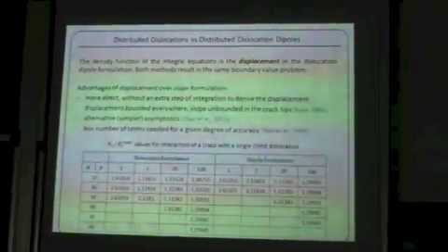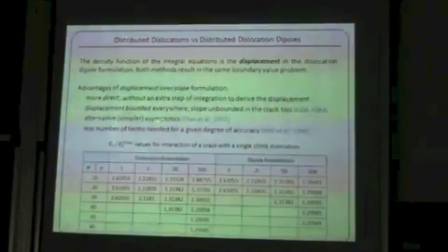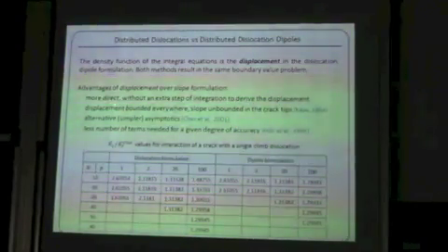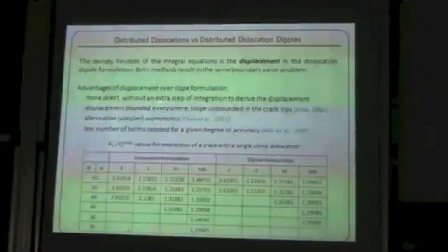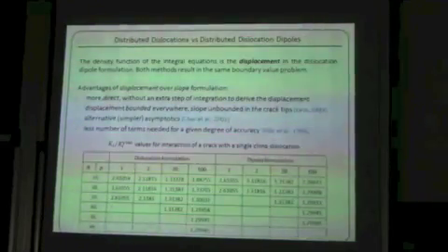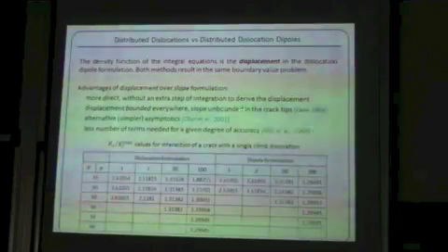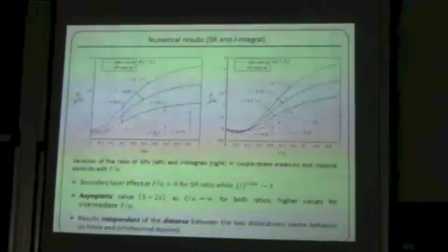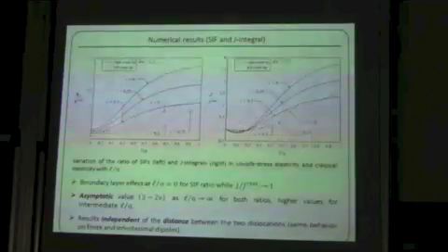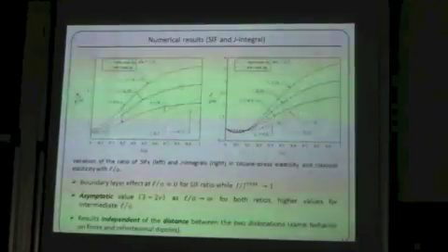Using both approaches. So we have written some advantages of this methodology that are reported by other authors as well. The most obvious is that this methodology is more direct, because we do not need an extra step of integration to obtain the crack face displacement, and also that the displacement is bounded everywhere, obviously, whereas the slope is unbounded. So these are some results using this approach for the interaction with a horizontal climb dipole.